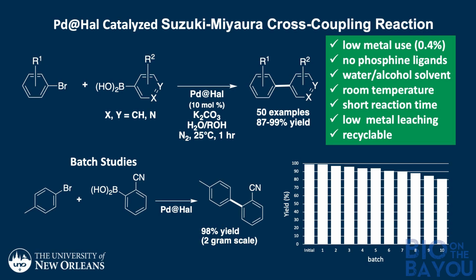The reaction was very tolerant of a variety of functional groups, but more importantly, we could execute this reaction in water, or water ethanol, or water propanol, basically these aqueous solvent systems. But what really caught us off guard, we didn't anticipate, was how much the reactivity of this system was enhanced. Reactions take place at 25 degrees, and typically reactions are complete in 1 hour. So that's a tremendous enhancement over essentially traditional coupling catalysts.